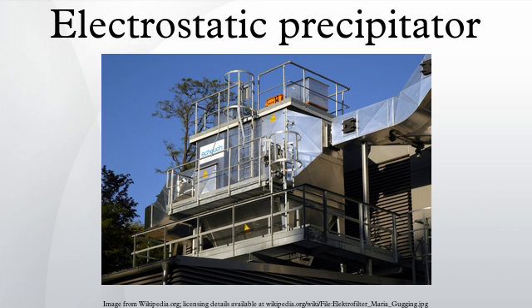In high resistivity dust layers, the dust is not sufficiently conductive, so electrical charges have difficulty moving through the dust layer. Consequently, electrical charges accumulate on and beneath the dust layer surface, creating a strong electric field. Voltages can be greater than 10,000 volts. Dust particles with high resistivities are held too strongly to the plate, making them difficult to remove and causing wrapping problems. In low resistivity dust layers, the corona current is readily passed to the grounded collection electrode. Therefore, a relatively weak electric field, of several thousand volts, is maintained across the dust layer. Collected dust particles with low resistivity do not adhere strongly enough to the collection plate. They are easily dislodged and become re-entrained in the gas stream.